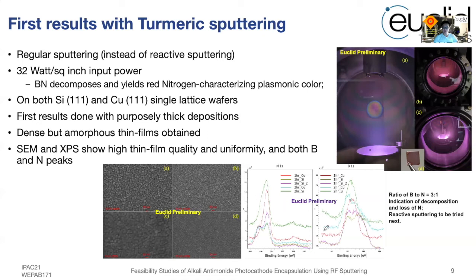The XPS shown in here shows that we had all the elemental components desired, including the boron and nitrogen. However, the ratio of boron to nitrogen is shown to be 3:1, which indicates that there was a loss of nitrogen, and we might want to consider reactive sputtering in the future to compensate for the lost nitrogen.